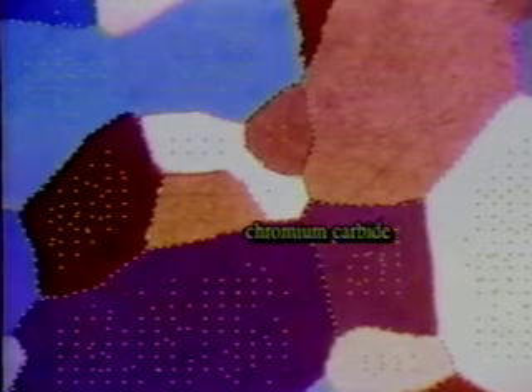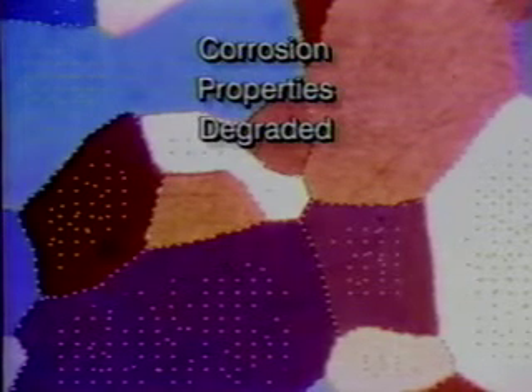At high temperature, the chromium atoms are evenly distributed in the crystal in a solid solution. And if an austenitic stainless steel is cooled quickly from a high temperature, the chromium atoms tend to stay in solid solution. But if an austenitic stainless steel is cooled slowly from a high temperature, the chromium atoms tend to combine with the carbon atoms. Chromium carbide will form near the grain boundaries. The material surrounding the grain boundaries is left deficient in chromium. Less chromium makes these areas of the steel less resistant to corrosion. This phenomenon is called sensitization.